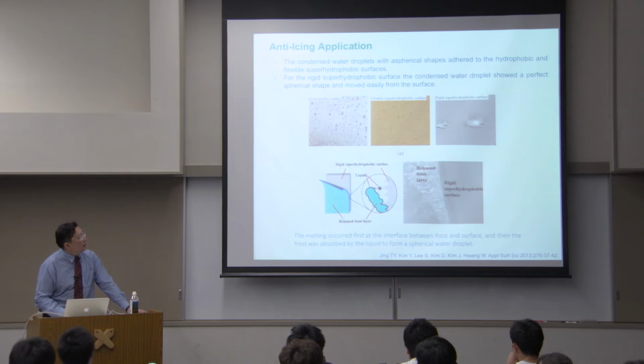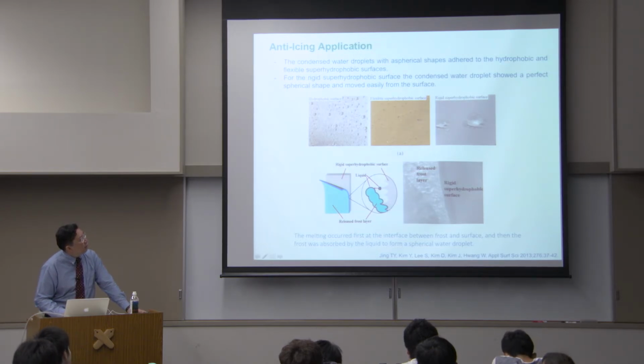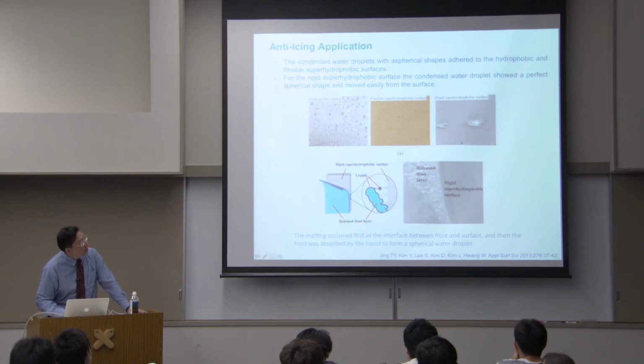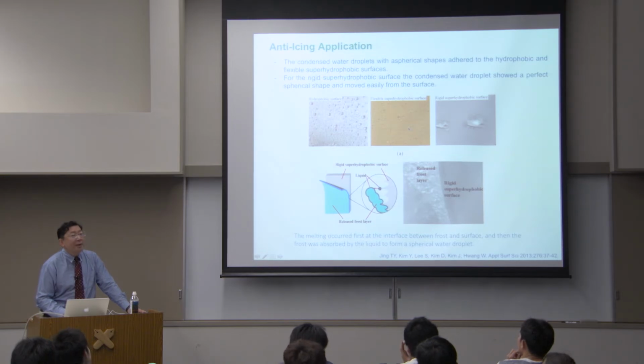You can see here different surfaces: a hydrophobic surface, a superhydrophobic surface, a flexible one, and a rigid superhydrophobic surface. This means that if you prevent liquid from nucleating on the surface to form ice crystals, one way to prevent ice formation is to repel them in the first place, or to prevent condensation.